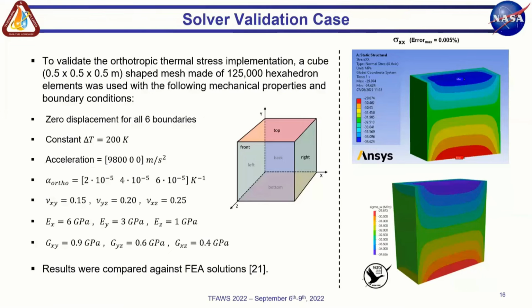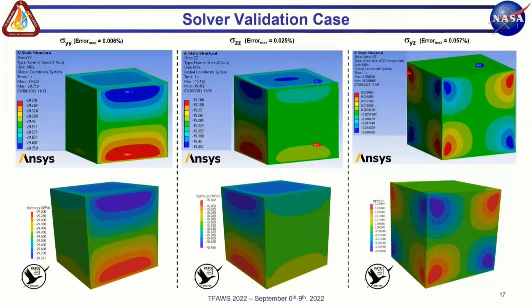The mechanical properties used are the ones shown here for the thermal expansion coefficient, Poisson ratios, the Young's moduli, and the shear moduli in the different directions. To validate the solver, the results were compared against the solution from ANSYS. And on the right, we can observe how there is a very good agreement between the simulation from PATO and the simulation from ANSYS for the stress in the x direction, and there is a maximum error of just 0.005%.